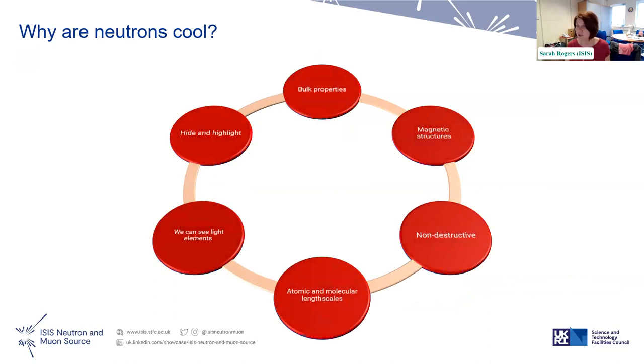So that means we can actually look at bulk properties of a material. We can look deep inside matter without having to chop open an aeroplane wing, or it means we can have lots of different sample environment with chunky windows, as long as they're designed out of the right materials. It means we can really do a lot of in situ measurements. You can look at magnetic structures. It's non-destructive. So if you have very delicate samples, such as for biology, you can guarantee that the sample is probably the same at the end of the measurement as it was beforehand. Sometimes with X-rays, you can get damage to the sample because of heating. We don't suffer from that.